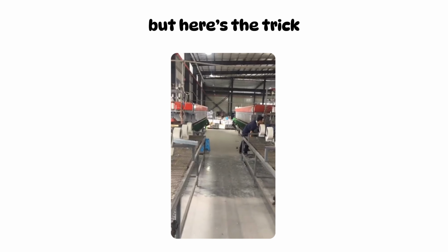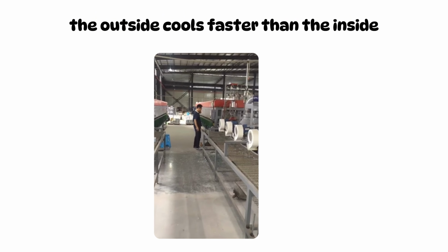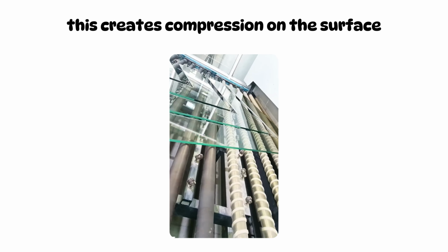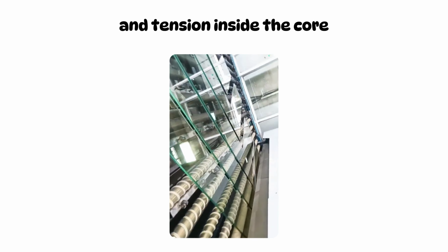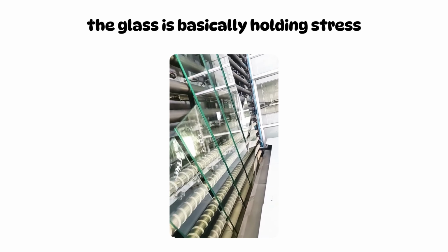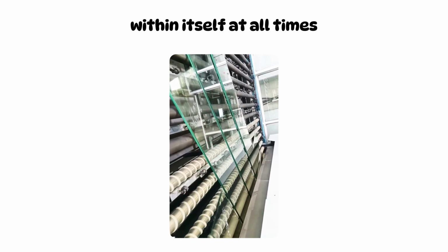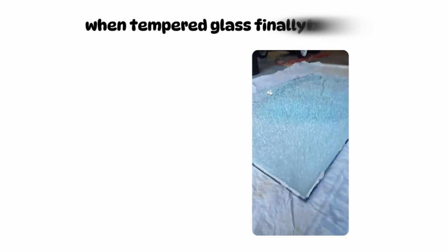But here's the trick. The outside cools faster than the inside. This creates compression on the surface and tension inside the core. The glass is basically holding stress within itself at all times. That stored energy is the key. When tempered glass finally breaks, it doesn't crack slowly. It releases all that energy instantly, shattering into thousands of small, blunt pieces.